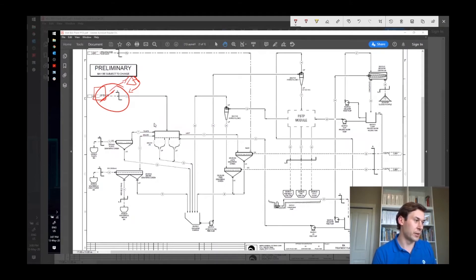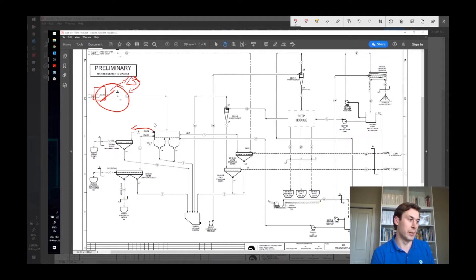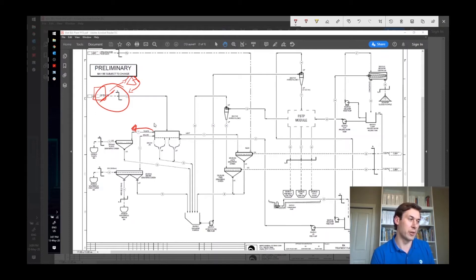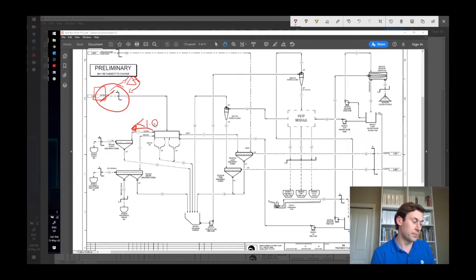There's a float stream, which will remove light plastics, organics, wood. Well, wood shouldn't be there, it should be pretty easily combusted. But the light plastics, the things that may not have been combusted in the incinerator just due to inefficiency or whatever. But anything with an SG less than 1.0 should be floating here and it'll get collected in a float bin.